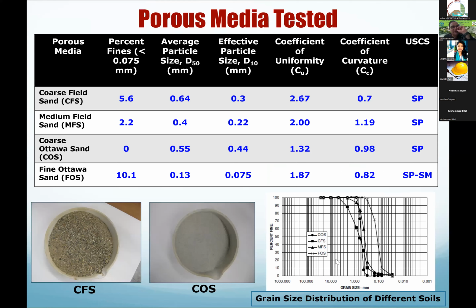So what we did is we tried to investigate the type of porous media, right? So the coarse sand, coarse field sand, medium field sand, and coarse Ottawa sand. This is more processed sand, like fine Ottawa sand. So this is from the processing plant, and these are actually field soils. And then we characterized the percentage fines and average particle sizes, based on the grain size distribution. These are all SPs and SP-SMs.